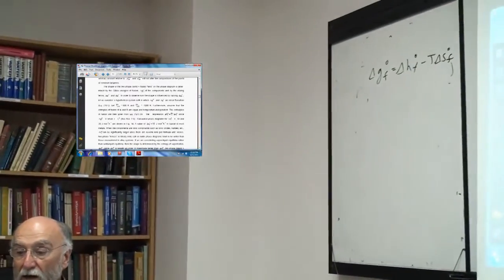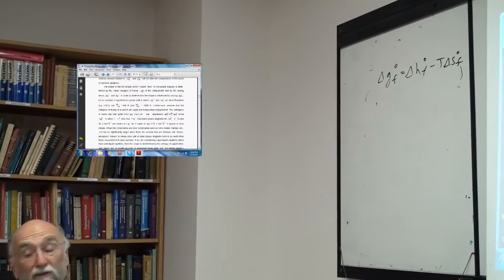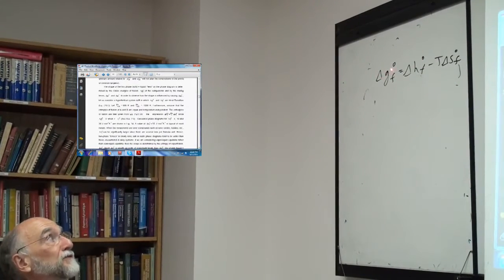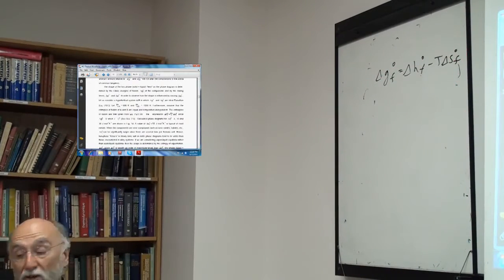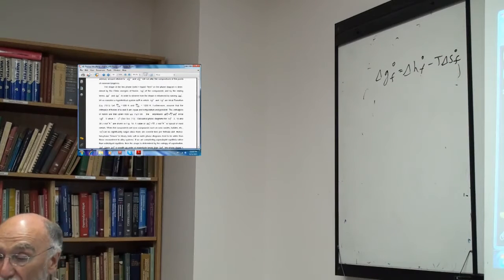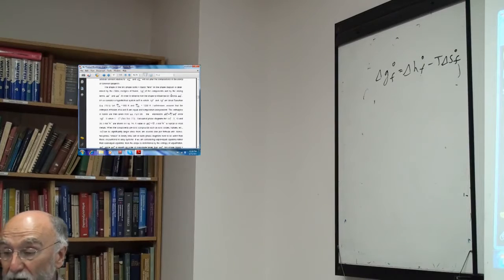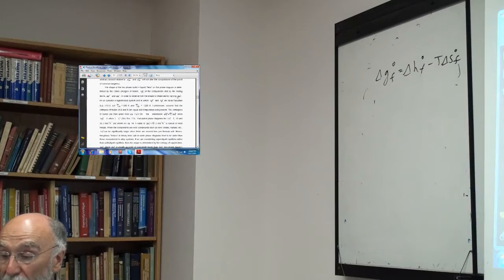Okay, so the two-phase lens on the phase diagram, the solid-liquid region, is determined by how two curves move relative to each other as the Gibbs energy of fusion varies with delta H minus T delta S. The temperature dependence of this Gibbs energy of fusion is the delta S naught fusion, and it's rather interesting to see how the shape of this two-phase region is influenced by varying the Gibbs energy of fusion.